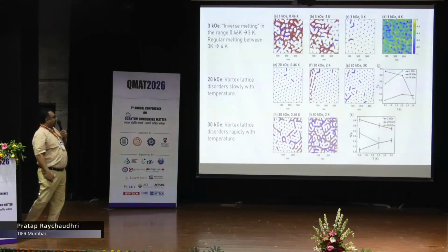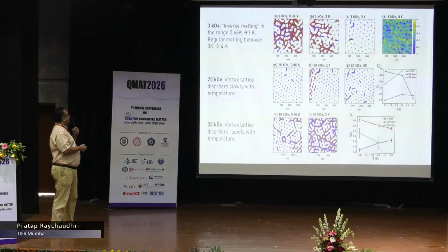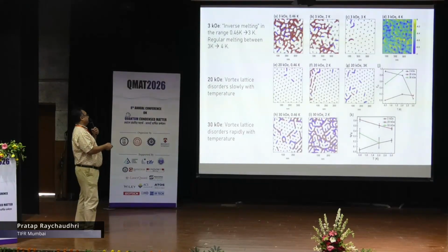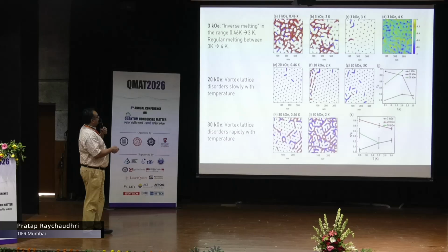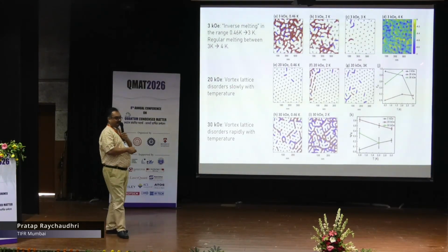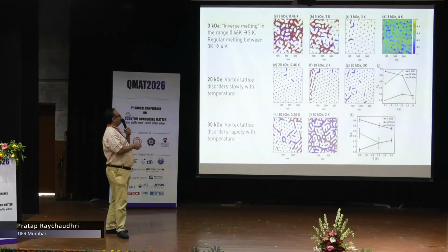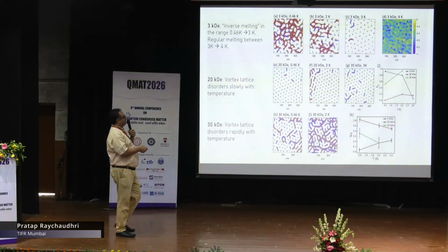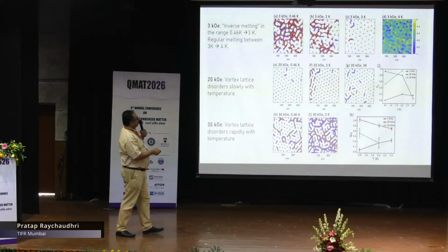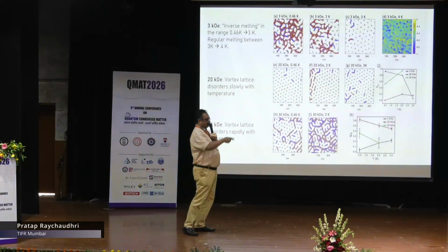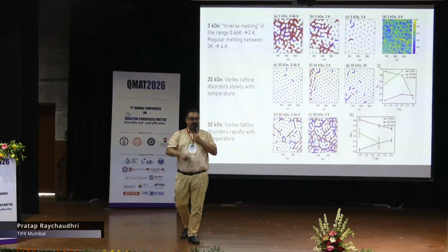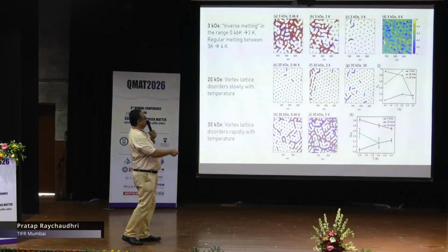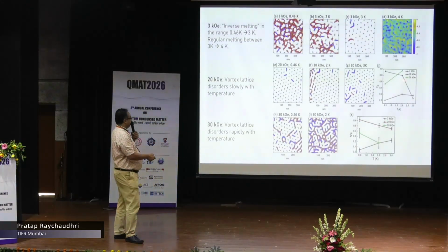So, what about as a function of temperature? I go to 3 kOe, and at a low temperature, again, this is the same thing as we have seen before, but now I increase temperature. You can see as I increase temperature at 3 kOe, I have almost a perfect vortex solid. So I have gone from an inhomogeneous liquid to a solid by increasing temperature, and from 3 to 4K, I suddenly have a melting. This is almost a first order abrupt melting, and here I cannot identify the minima, so I am just showing you the image.